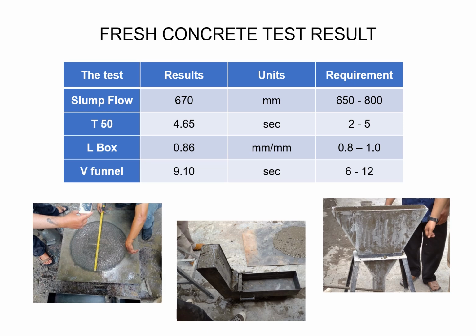Fresh concrete test results. Slump flow test 670 mm, T50 slump flow 4.65 seconds. L-shape box test 0.86. V-funnel test 9.1 seconds. All HVFA-SCC tests fulfill the requirements.